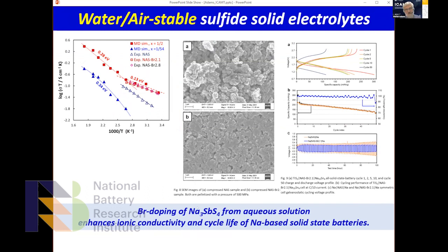We treat lithium and sodium as very, very similar. So you will see some results for lithium conductors, some results for sodium conductors. And because we can work in water, it's very easy to do some doping, because we just throw the dopant into the solution, and when it crystallizes, you have some of the dopant also in the material.